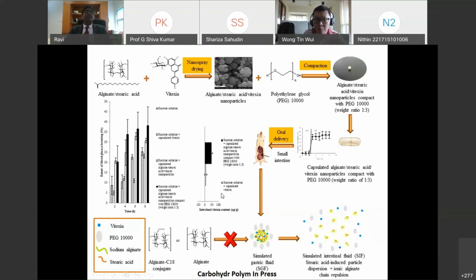Now you can see that if we replace the alginate stearic acid mixture with alginate alone, there will be no favorable pharmacodynamic performance. Likewise, if we replace the alginate stearic acid mixture with an alginate stearic acid conjugate, the ideal pharmacodynamic actions will not be attained, right? Alginate alone will not function very well because there's no wicking action of the stearic acid. And by conjugating the stearic acid onto the alginate, you actually restrict the stearic acid movement. So the wicking action of stearic acid is not there, and hence your nanoparticles cannot be dispersed so well in the intestinal regions to release the vitexin, right?